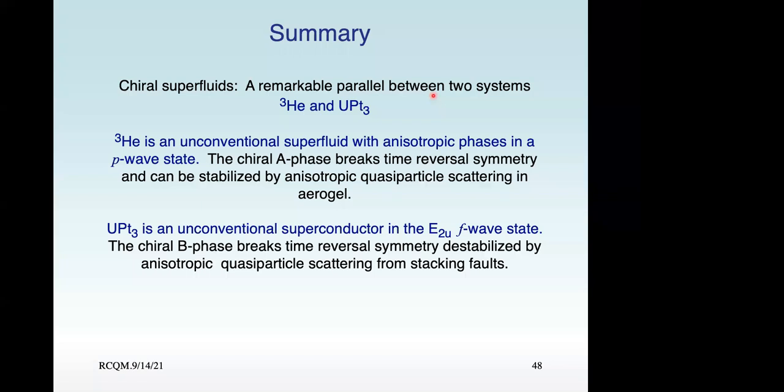Yeah, so I looked at it. If you start from zero field, you have a symmetry breaking field that's preferring the A phase over the B phase, something that's breaking the two-dimensional representation into two nearly degenerate one-dimensional representations. So you have two states close by. Now, if you turn on a magnetic field, you have another symmetry breaking field, which is the Zeeman coupling to the orbital angular momentum of the Cooper pairs.